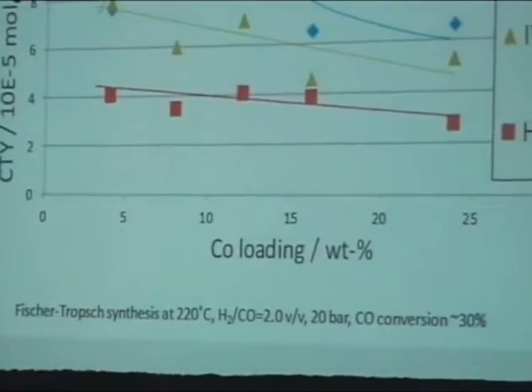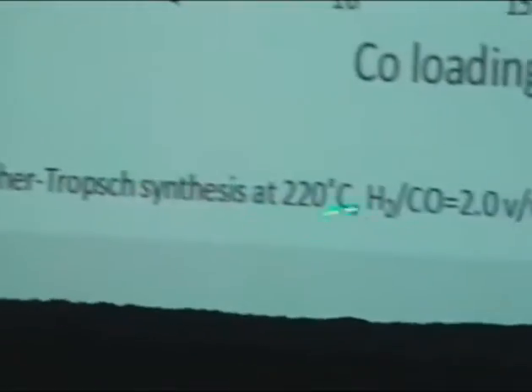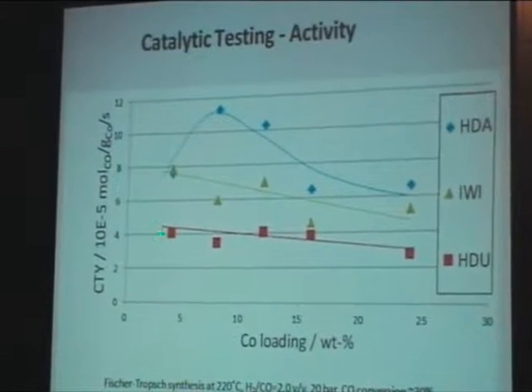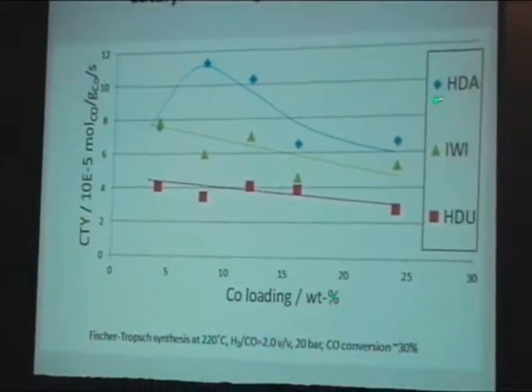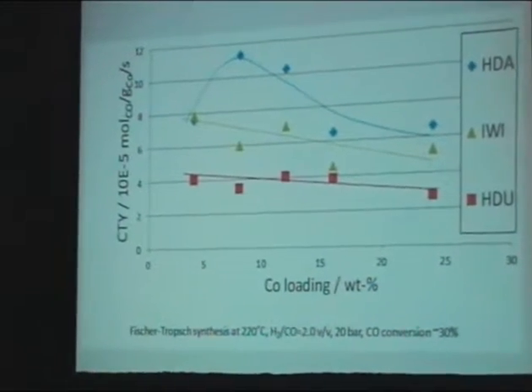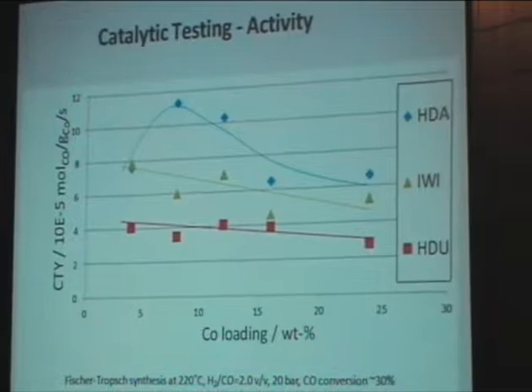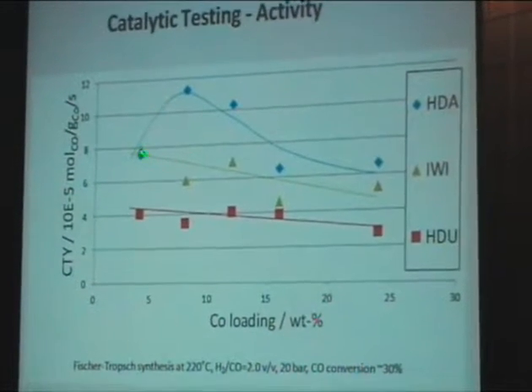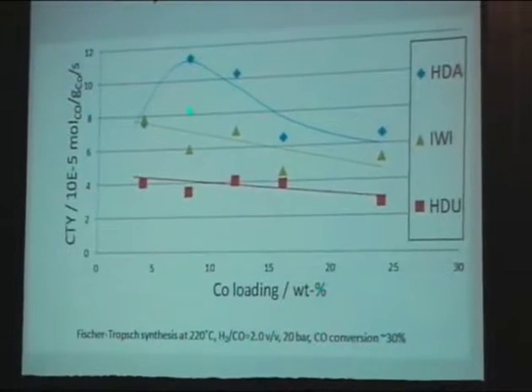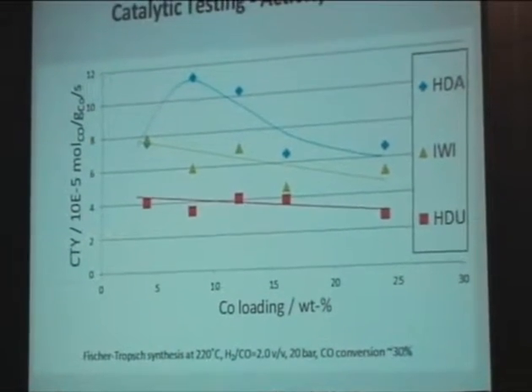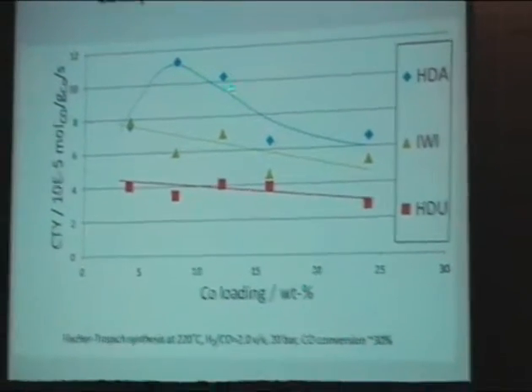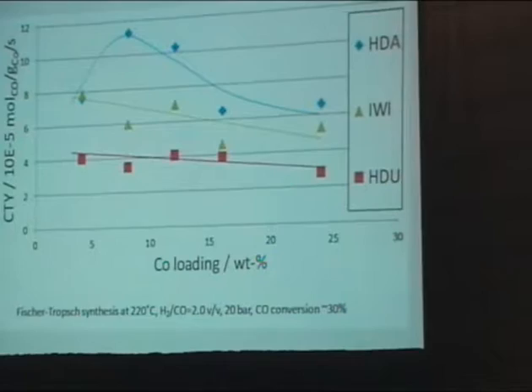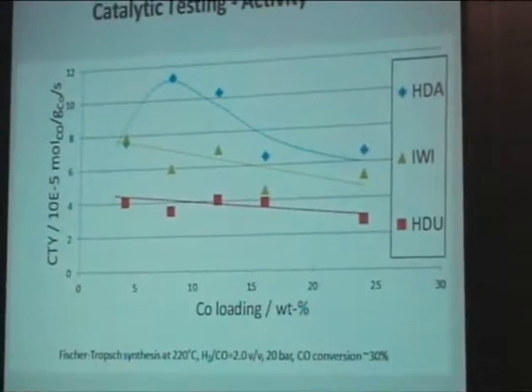First of all, the activity, the cobalt time yield, now plotted per gram of cobalt, the activity as a function of cobalt loading. Here are the conditions. There's some variation in conversion. I think the maximum was about 20 to 40% CO conversion. And what we observe is that there's a clear advantage of this ammonia precipitation method, which has been patented by Johnson Matthey. Martin Locke was one of the inventors of that, where it's clear that at intermediate loadings there is a great benefit, probably through dispersion. From our characterization, it's mainly a dispersion effect. When we go to high loadings, it more or less converges, more or less gets independent of the method we use.